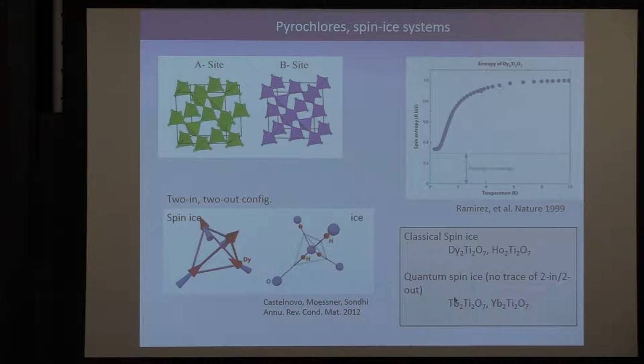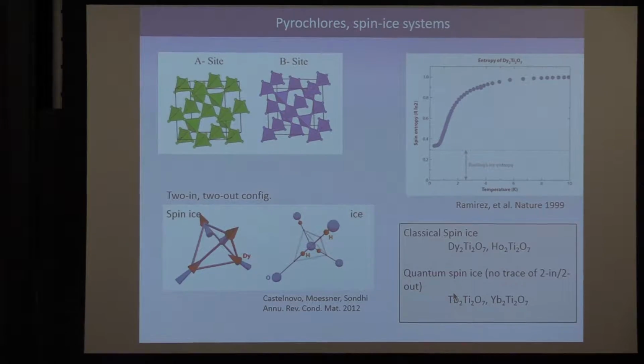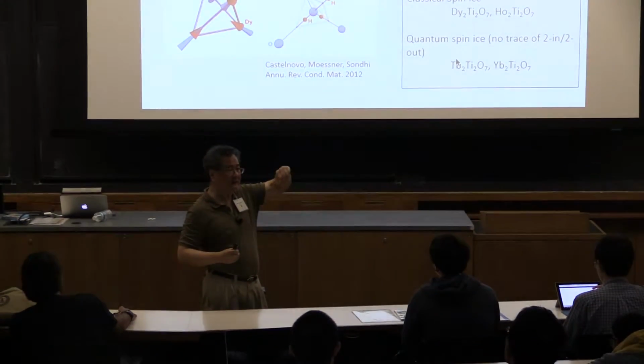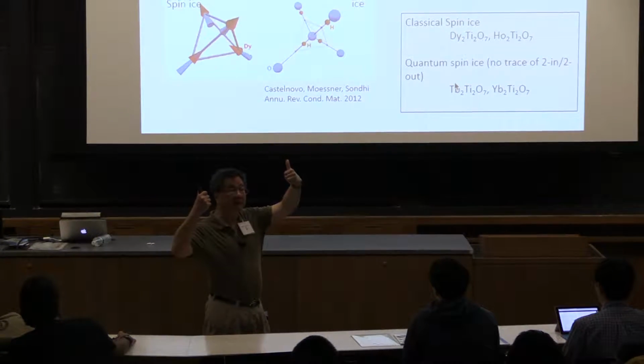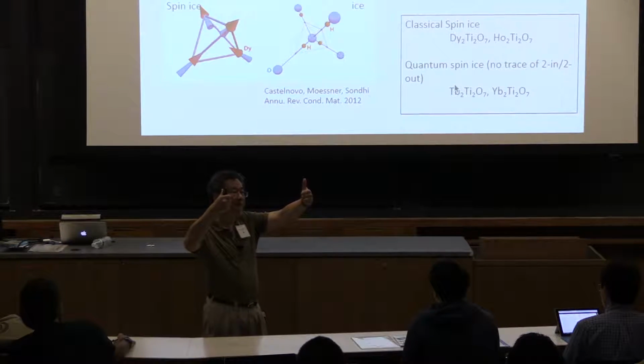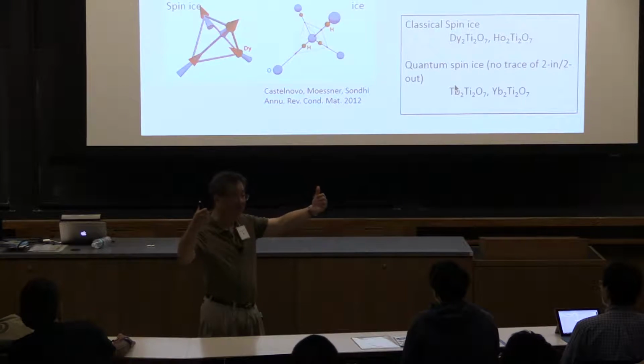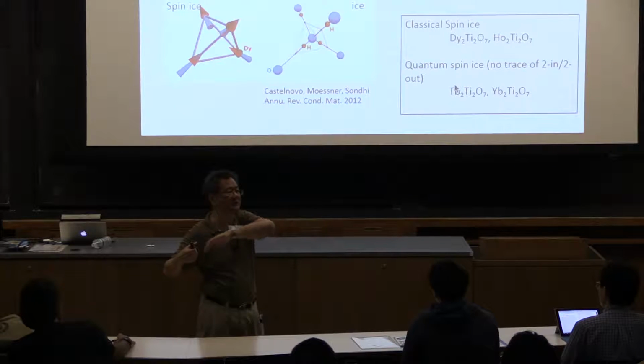You said that you can have spin ice in the quantum spin ice. Yes. How is this related or different from spin glass? Completely different. Spin glass is the following. You take copper, pure copper, and you stick in a lot of manganese atoms. This is the canonical spin glass. Okay, so imagine copper with a dense collection of manganese. So manganese has a local moment, right? However, the manganese separation is completely random, right? So it has a Gaussian distribution, right?